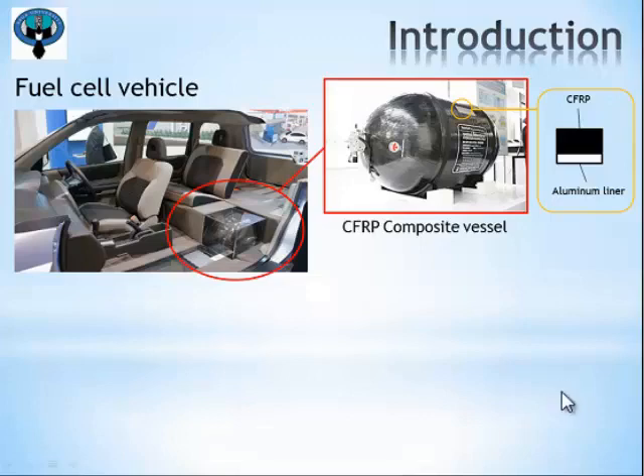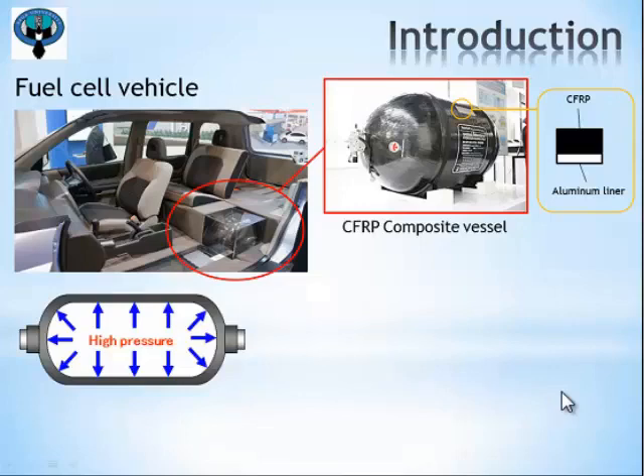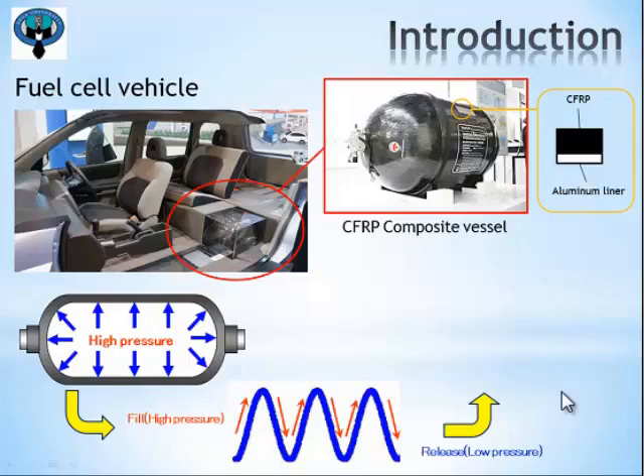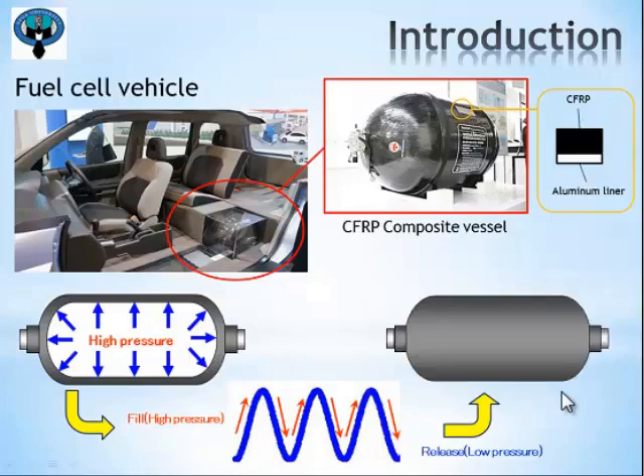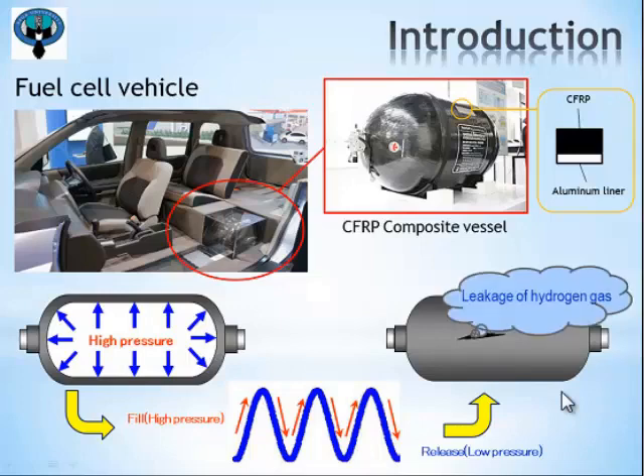For driving the vehicle, this pressure vessel is repeatedly filled and released by high-pressure hydrogen. Such processes induce fatigue cracks in the aluminum liner, and finally, progressed cracks penetrate the aluminum liner and hydrogen gas leaks through the cracks. The goal of our study is to detect such fatigue cracks of composite vessel before penetration.